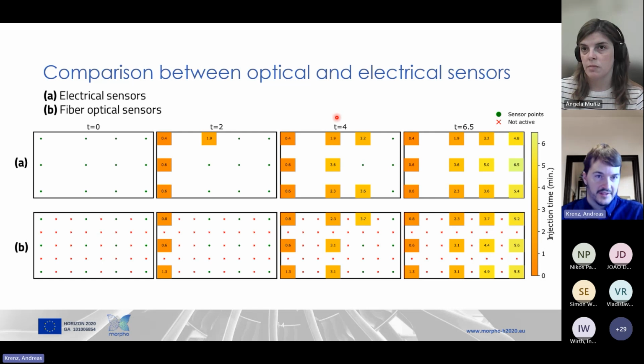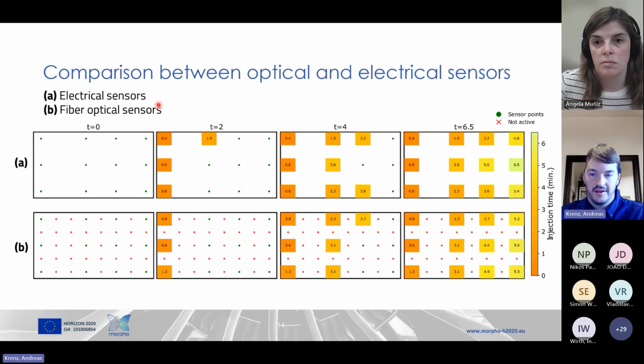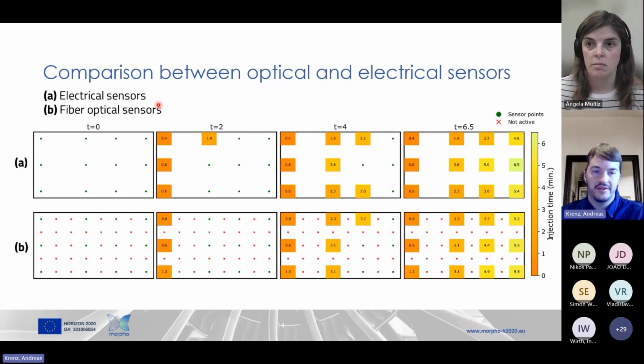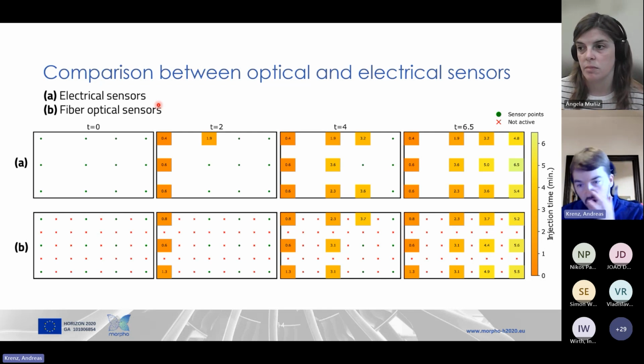And the main reason for this is that the FBG sensors are positioned on the inside of the preform, while the electric sensors are on the inside of the mold, but on the surface side of the part. And so we have this kind of description of the offset which occurred there. And if you use both techniques for this resin flow, it makes it possible to investigate the flow behavior of the resin in the component cross section, and this provides important process knowledge too.